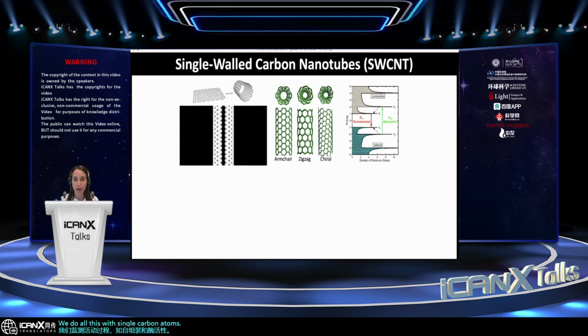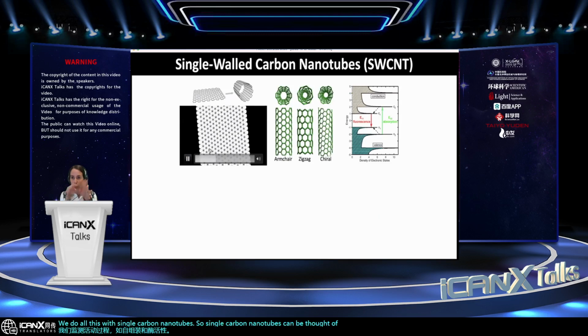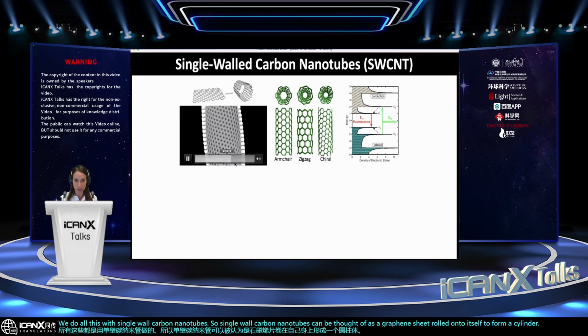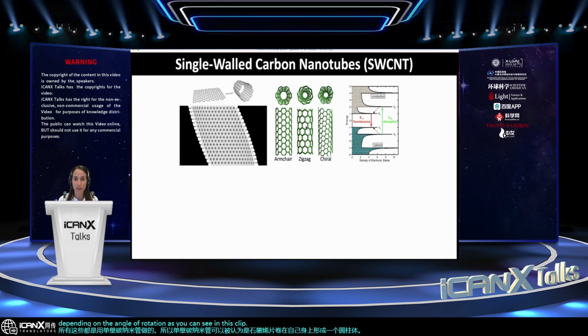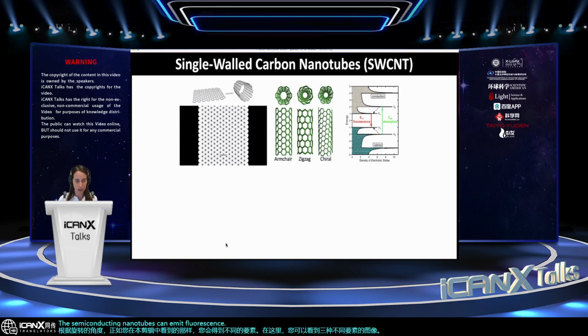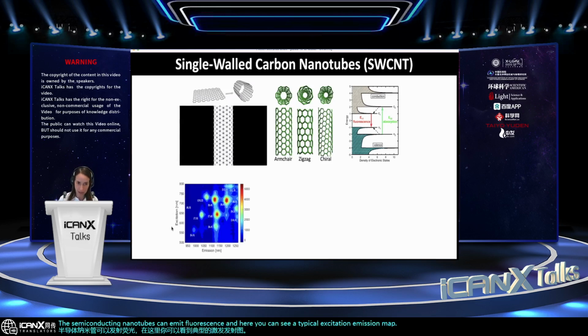So single-wall carbon nanotubes can be thought of as a graphene sheet rolled onto itself to form a cylinder. Depending on the angle of rotation, as you can see in this clip, you get different chiralities. Here you see images of 3 different chiralities. The semiconducting nanotubes can emit fluorescence. And here you can see a typical excitation emission map. The y-axis is the excitation wavelength, and the x-axis is the emission wavelength, and the color codes for intensity. You can see that the emission is within the near-infrared range between 900 to 1400. Here you can see different peaks. Each peak corresponds to a different chirality.